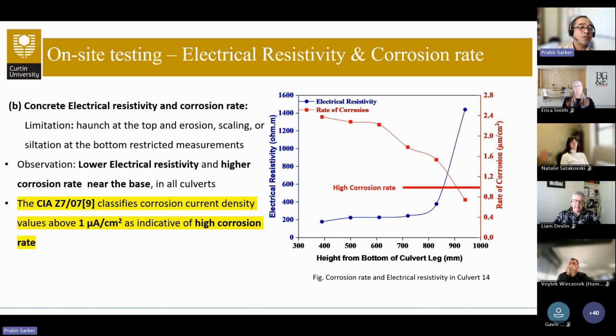The observation was that there was low electrical resistivity and high corrosion rate near the base, as we can see in this diagram. The horizontal axis is the height from the bottom of the leg, and the vertical axis is the electrical resistivity on the left hand side and the rate of corrosion on the right hand side. The red line shows the corrosion activity.